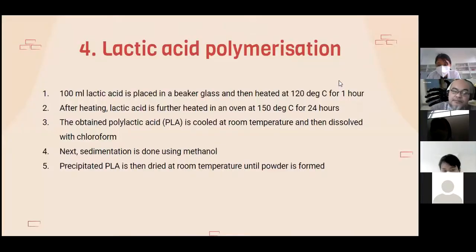Next, after the lactic acid is produced, it is polymerized. So 100 milliliters of lactic acid is placed in a beaker glass and then heated at 120 degrees Celsius for 1 hour. And after heating, the lactic acid is further heated in an oven at 150 degrees Celsius for 24 hours. And then the obtained PLA is cooled at room temperature and then dissolved with chloroform. After that, sedimentation is done using methanol. From this process, the precipitated PLA is then dried at room temperature until powder is formed.